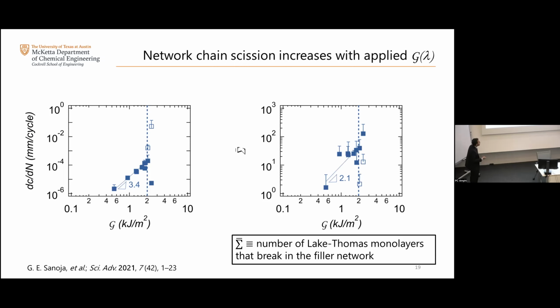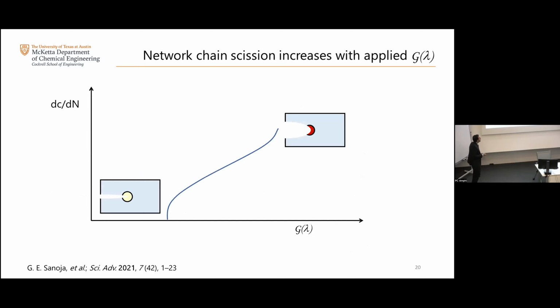Okay, so that's one of the second conclusions that I wanted to show you. If I want to boil this down to a scheme, effectively what you have is that at very low deformations, you have low damage, and I'm indicating that with a yellow color. And at very high deformations, your crack tip is more blunted, and effectively you have more damage, which I'm indicating with the red color when you get to the fracture point. So again, Lake and Thomas picture incomplete because your damage depends on the stretch that you actually apply to the